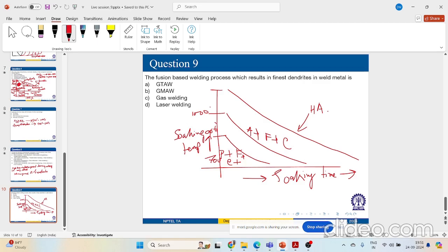Now, my cooling rate will also affect it. Like peak temperature, the cooling rate experienced by the heat affected zone will be maximum at the fusion boundary, and then it keeps on decreasing gradually on moving away from the fusion boundary towards the unaffected base metal. So this coarser austenite in the heat affected zone, which I mentioned as the coarse grained heat affected zone, will tend to form martensite, while austenite in the fine grained region may form fine pearlite along with some pre-existing pro-eutectoid ferrite structure, right? So in a very narrow region next to the fusion boundary, a large variation in microstructural and mechanical properties can be observed.